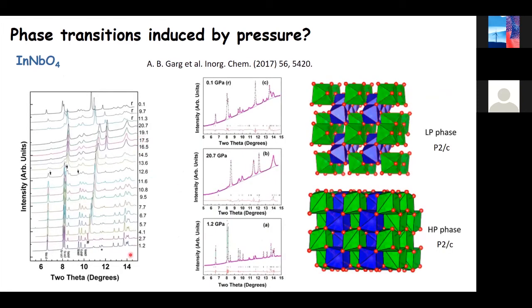These are results in indium niobate. The results in indium niobate are very comparable to those in indium tantalate. The only thing is that the transition only completely happened at 20.7 GPa, which is close to the highest pressure we reached in the experiment. But again, the transitions are reversible. 1.2 GPa and 0.1 after pressure release give the same structure.